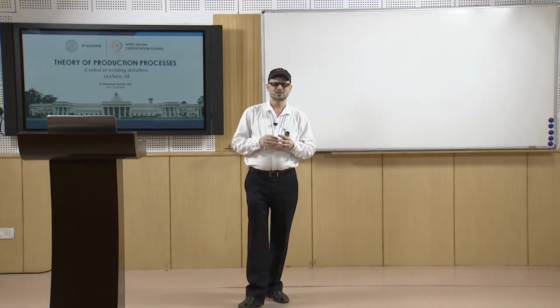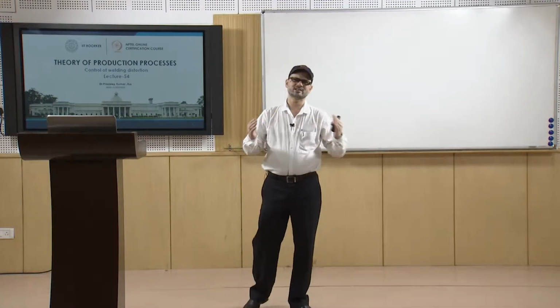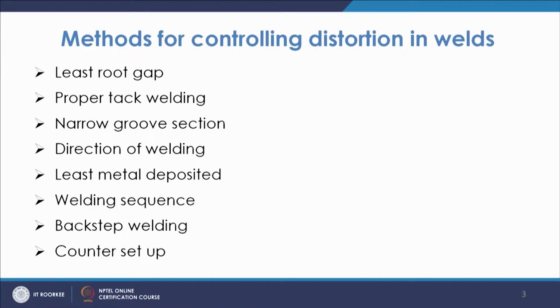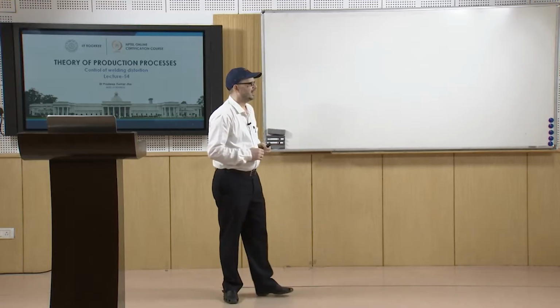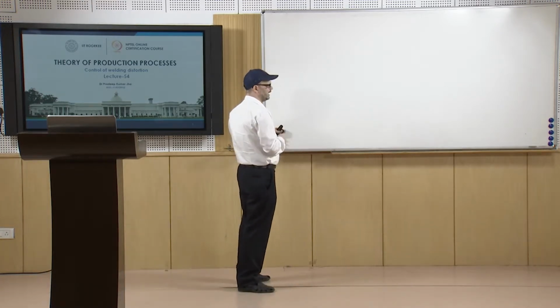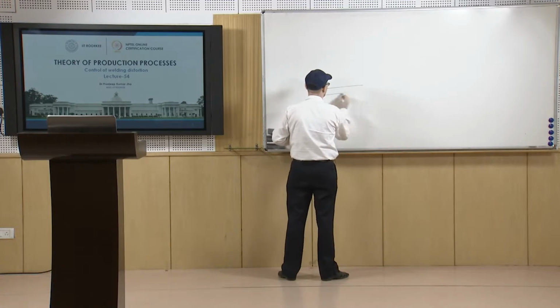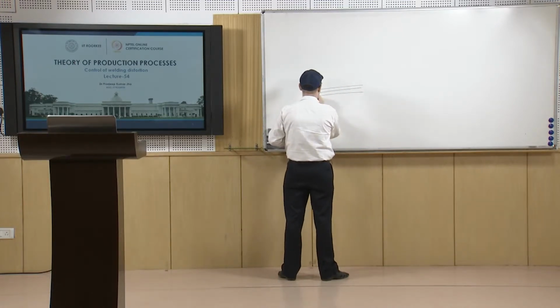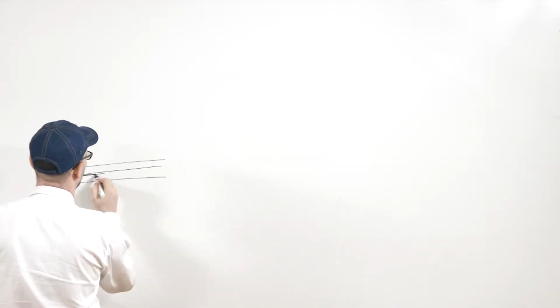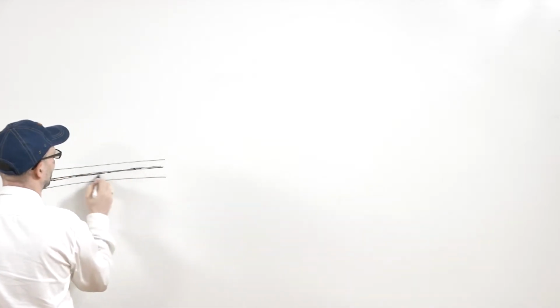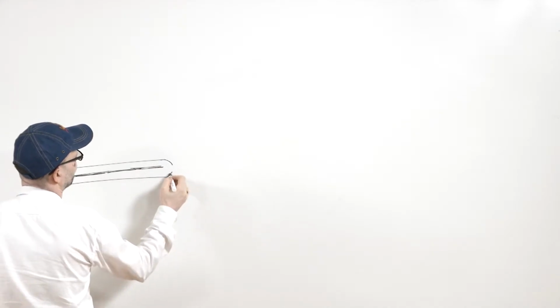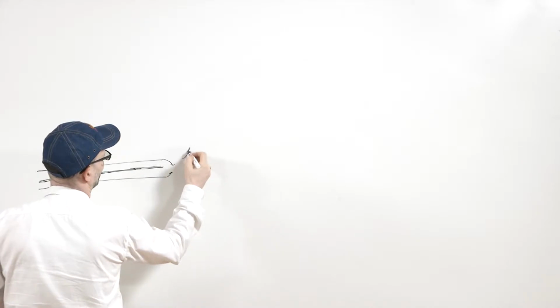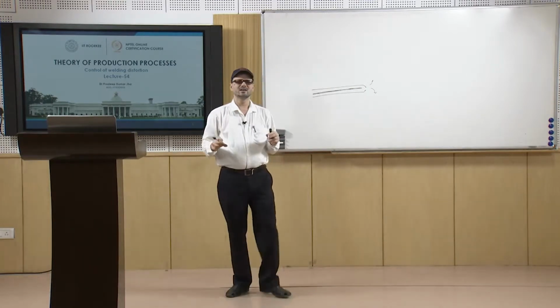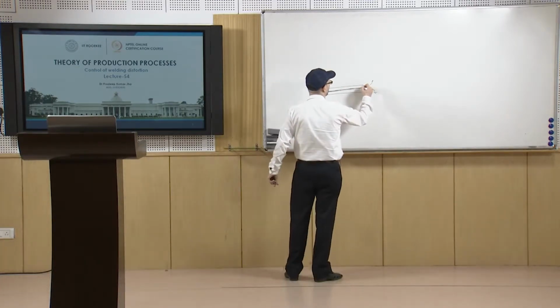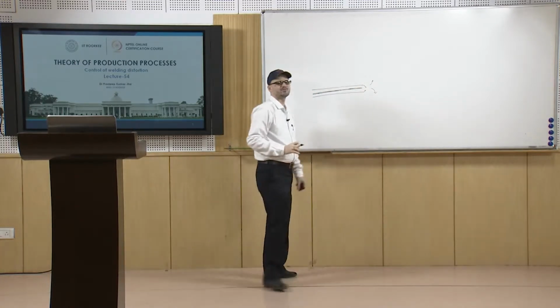This is basically done to control the distortion, because we have seen that especially in the rotational distortion areas, you are welding along a line, and as you reach towards the end, suppose this is the weld line and this is the longitudinal direction, either this may go like this, or this may go like this. So, what we normally do is tacking, so that you are fixing these points by using the tack welds.